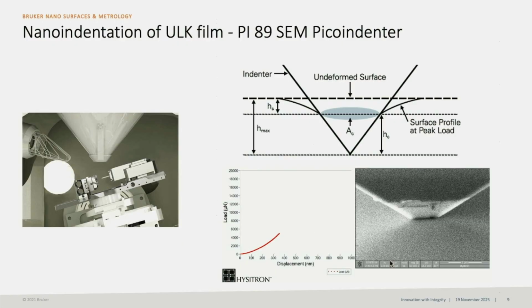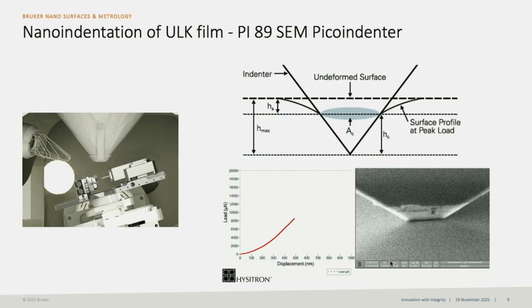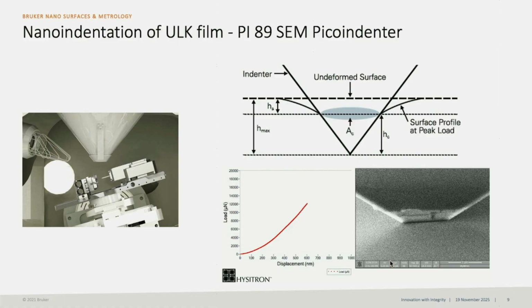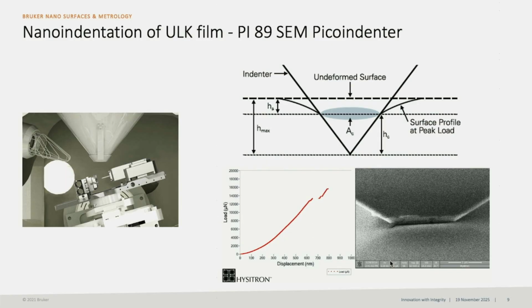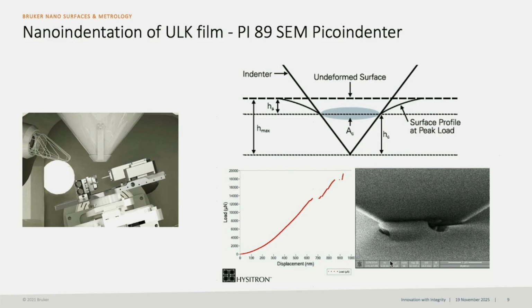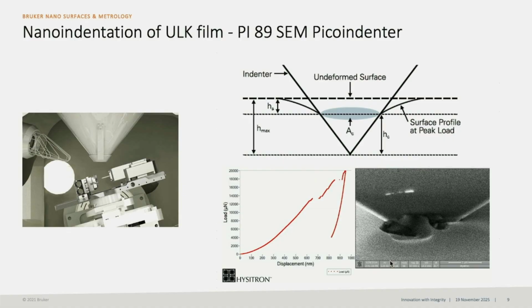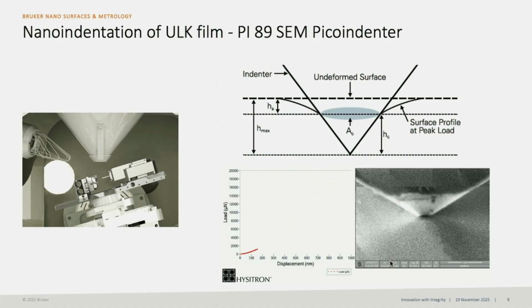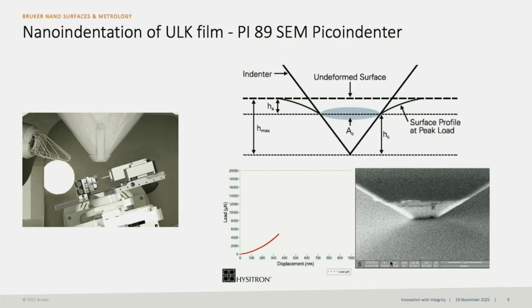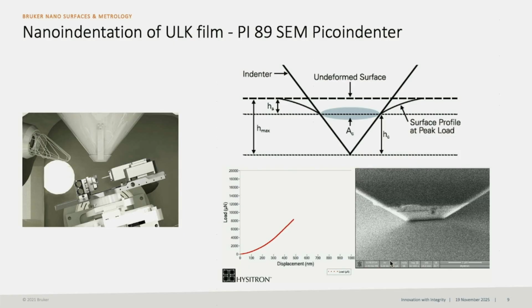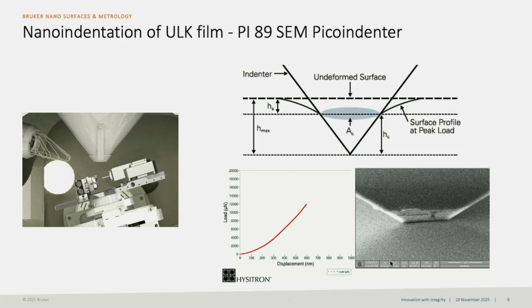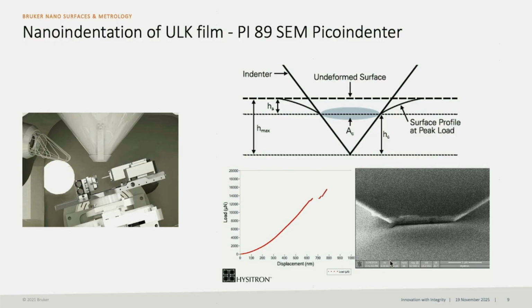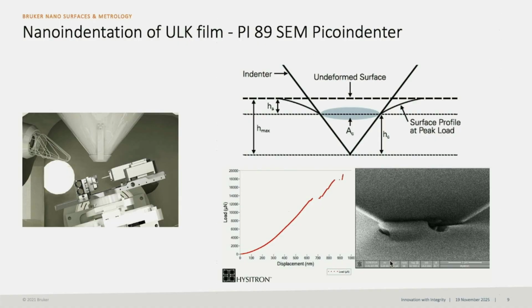So there is another example for the nano indenter on the same thing. You look at this, this is our machine inside of the SEM, right? We tilt the angle, then we can see the indenter and the tip. With the nano indenter, we can measure the hardness and modulus by the mechanical model, but sometimes we can see some strange signal in our force displacement curve. This we call the pop-in signal. If you look at the curve, it's very smooth in the beginning. Then when we see the pop-in, we see something happen. So this is cracking, and we continue to measure. This is another pop-in here. That is representative of the material change.